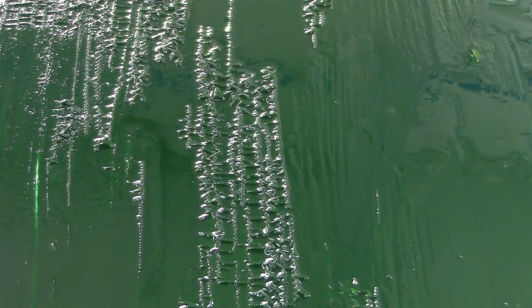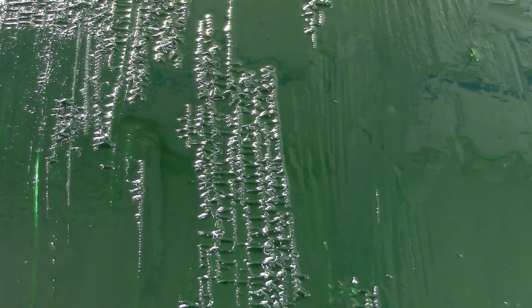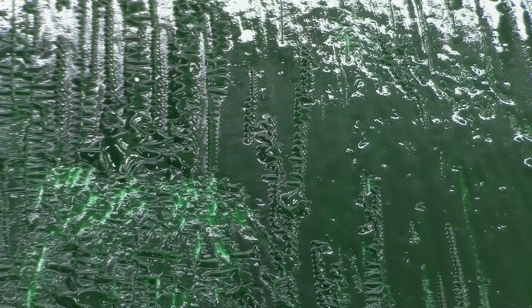See here how the styrene attacks and lifts the Gelcoat, following the lowest points first where the brush lines are, basically where the Gelcoat is at its thinnest, and also most likely at its softest straight after curing. The same will happen if you're applying a second layer of Gelcoat which takes too long to cure. If your resin or second Gelcoat cures within a decent timescale, the styrene will not have a chance to do this to your Gelcoat.